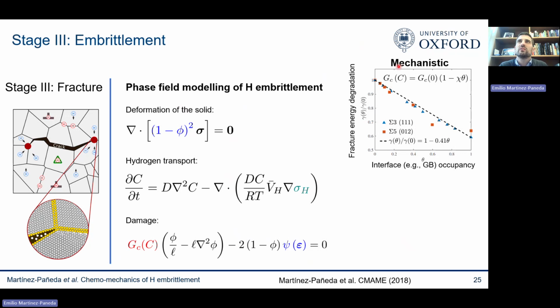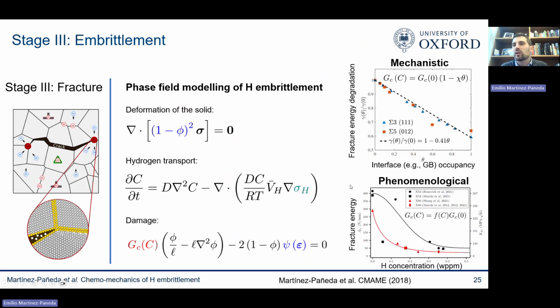Based on this DFT calculation that we do once in our lifetime offline, we can directly input that into our model. But working with industry, a lot of industry partners tell us as well, we don't really trust atomistics that much, and in any case, we have a lot of data of fracture energy versus hydrogen concentration. So why don't we just feed that data and incorporate that into our model? This is something you can do, of course.